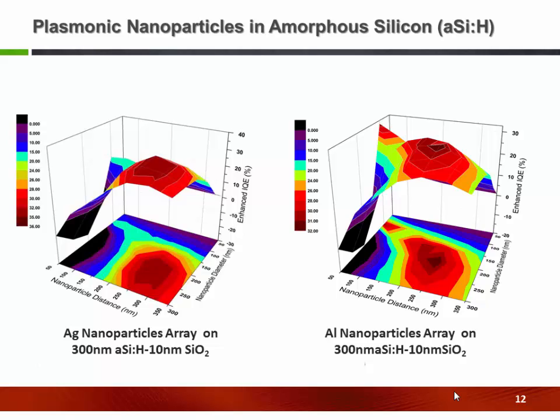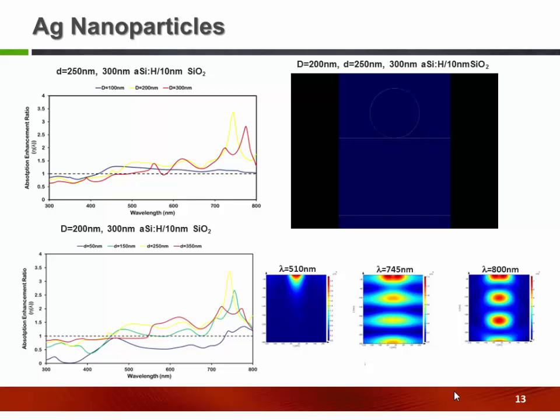To further investigate the performance, one good example is that we could investigate the absorption and transmission ratio at different wavelengths. Specifically, this is very critical because we want to see at what cost this enhancement is obtained. By investigating the absorption ratio, we see that below about 400 to 450 nanometers we don't have any enhancement. Actually, we reduce the absorption ratio because of the parasitic absorption in the metallic structure itself.